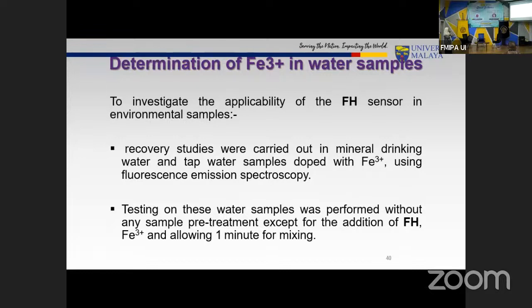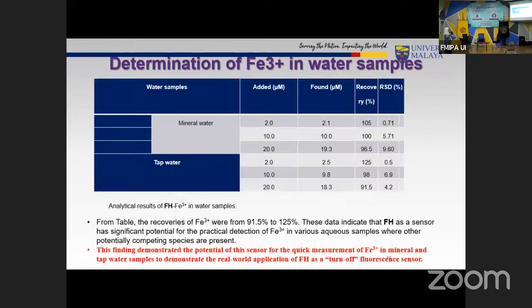So what my student was trying to investigate is the applicability of our sensor in environmental samples. So she studied the recovery studies carried out in mineral drinking water as well as tap water, with water samples doped with Fe3+, using fluorescence emission spectroscopy. And the testing of the water samples was performed without any sample pre-treatment at all, just very rough samples. And this is all the preliminary result. You cannot say much about this result, just to share with you that it can be done, but further work is now going on in our lab.